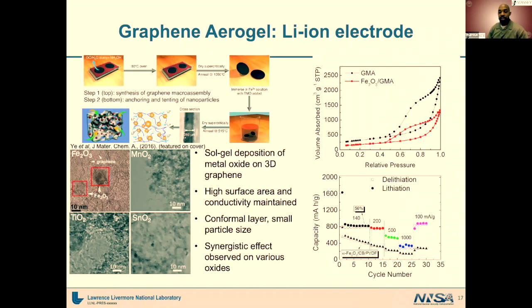So now just moving to some of the applications. Here we're showing that we're able to use these materials for lithium ion electrodes or lithium ion batteries. In this case, we're able to deposit various metal oxides, which are good storage materials for lithium, onto our conductive graphene aerogel and get fairly good performance from them.